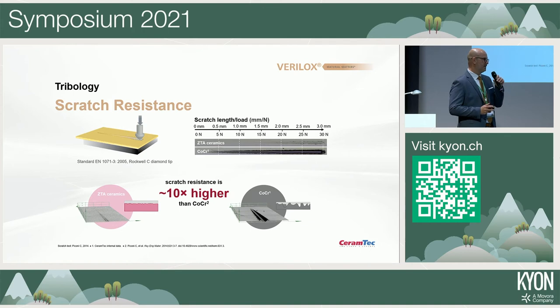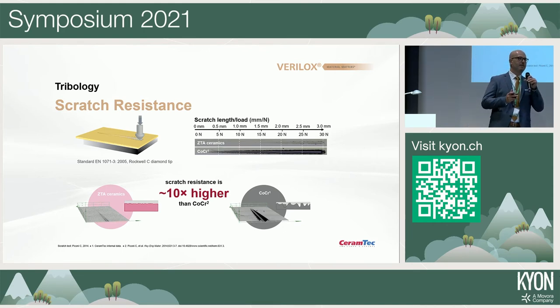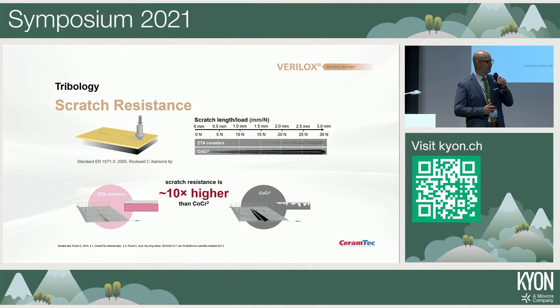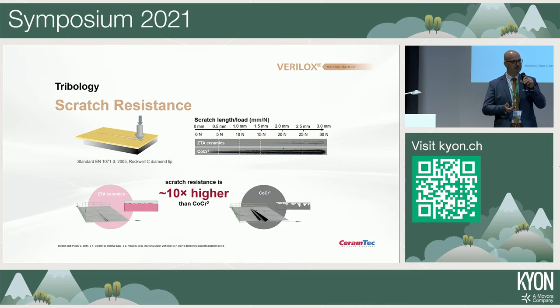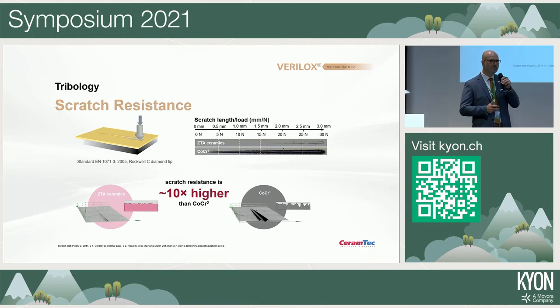And what you see in these tests are two things, two differences in comparison to metal. The first one is that you get a much later appearance of the scratch, so you need a higher force to apply a scratch. Second one is the scratches are not as deep as in metal, and the third one is due to the effect that you don't have any plastic deformation in ceramics, you don't get any elevations on the rim of the scratch. So you don't see the classical burrs that you know for metal pieces. And that's important if you combine the ceramic component, the ceramic surface, with a weaker material like we do in the hip implants. Since we have no burrs here on these scratches, we protect the weaker component from abrasion.